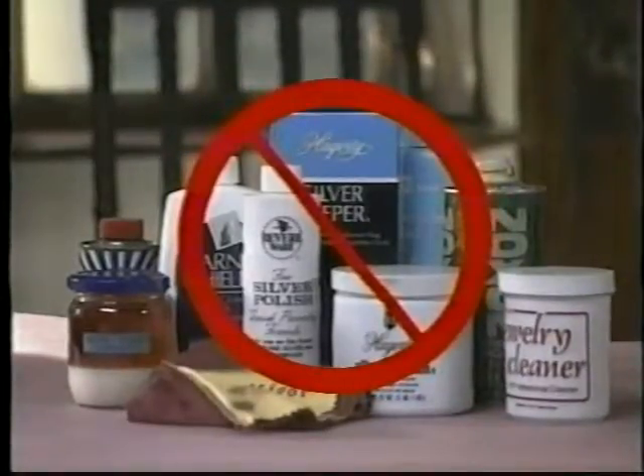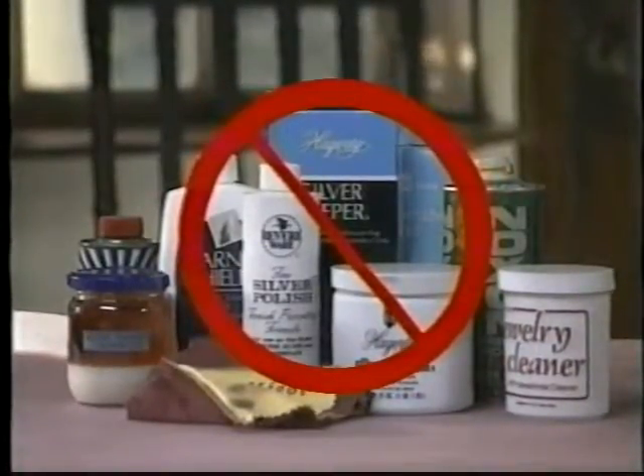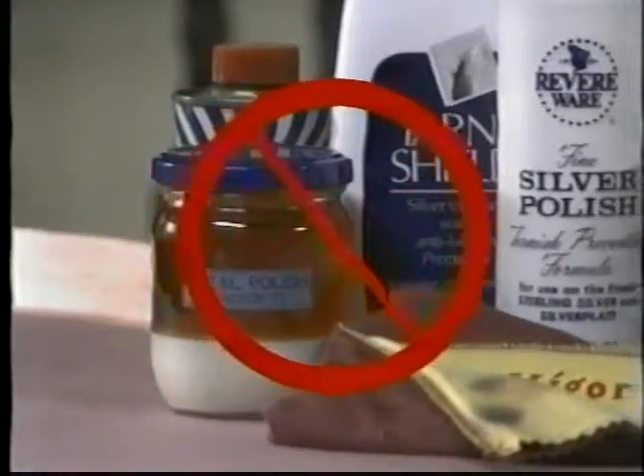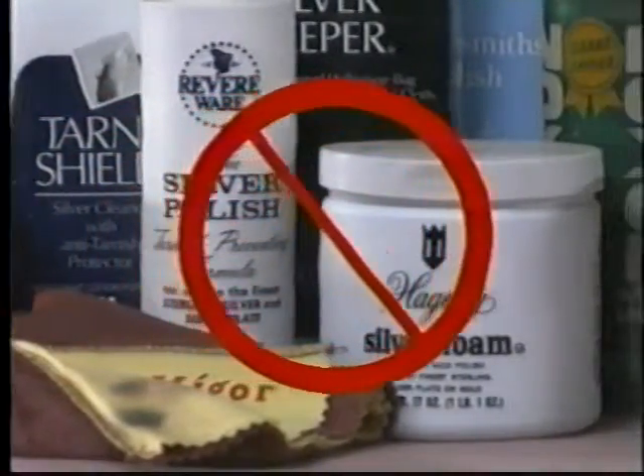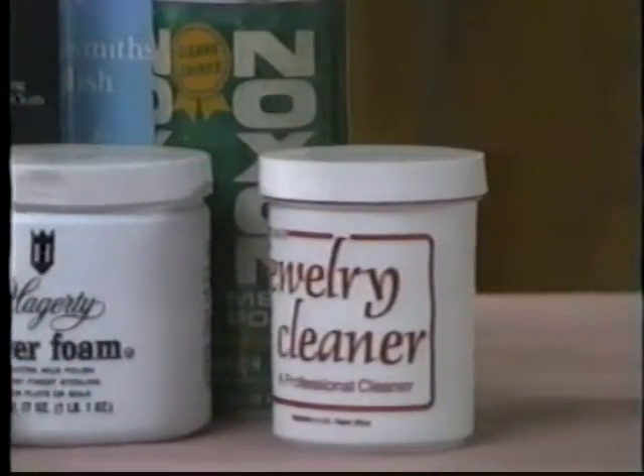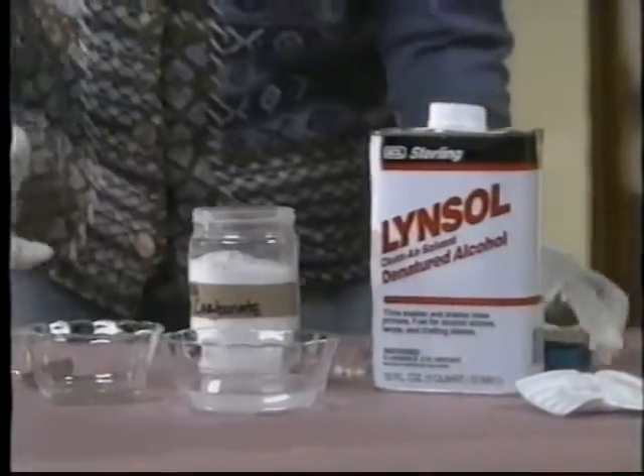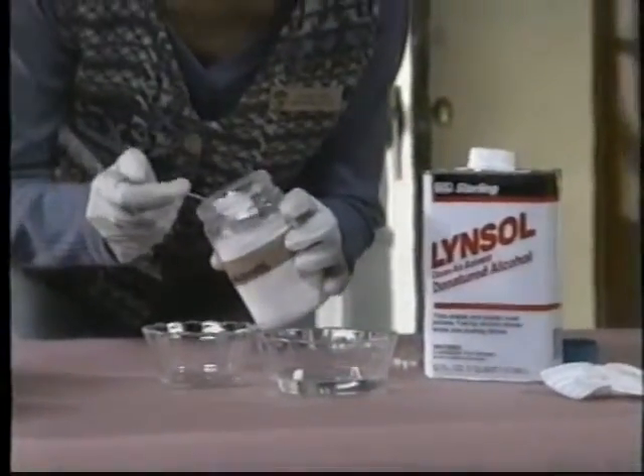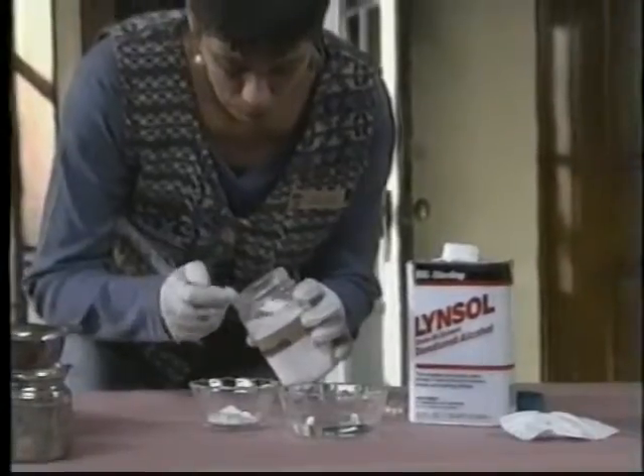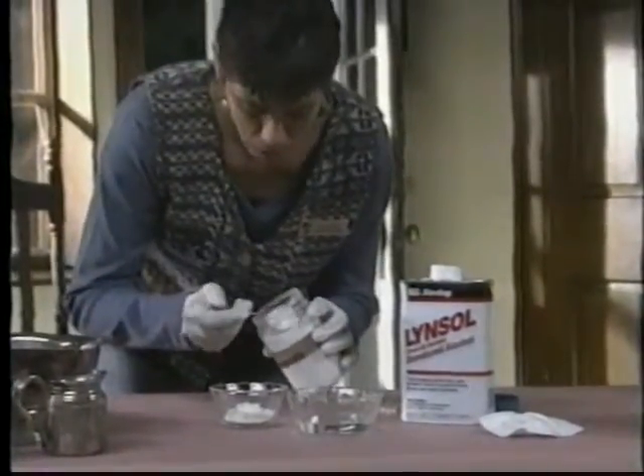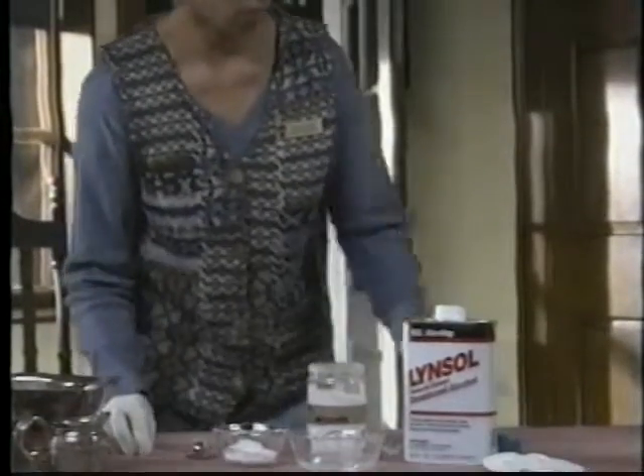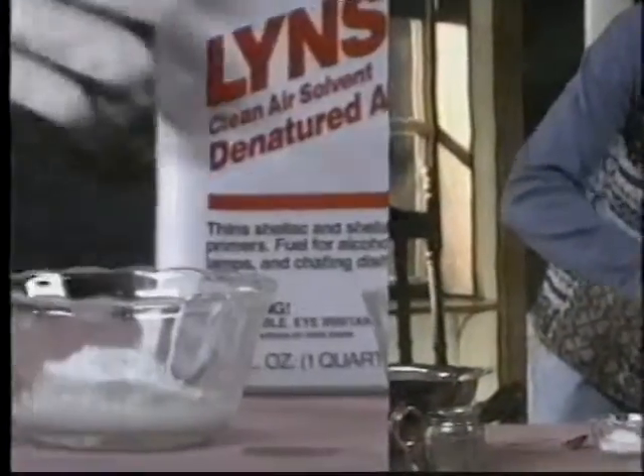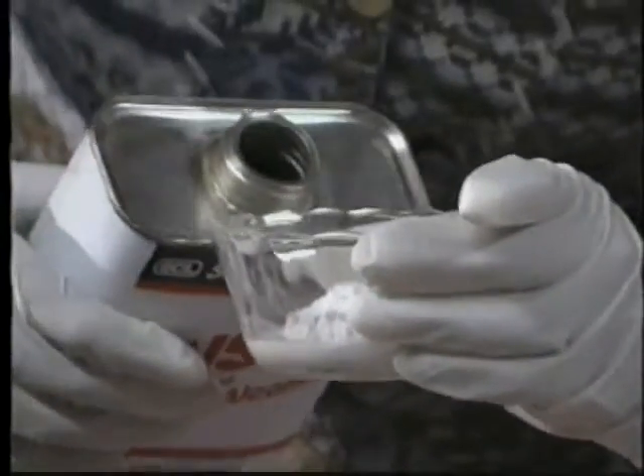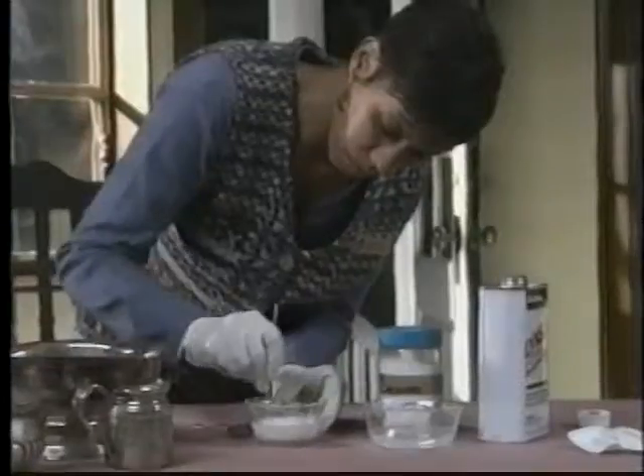Regardless of how stable the object is, commercial polishes like these should never be used. Many contain corrosive chemicals or harsh abrasives that can permanently damage surfaces. Some contain tarnish inhibitors, which have been found to cause long-term damage to metals. The safest and most effective polish is one you'll make yourself. Mix a thin slurry, the consistency of cream, from precipitated calcium carbonate, available at conservation supply stores, and ethanol or denatured alcohol. Do not substitute ground chalk, as it can scratch instead of polish.